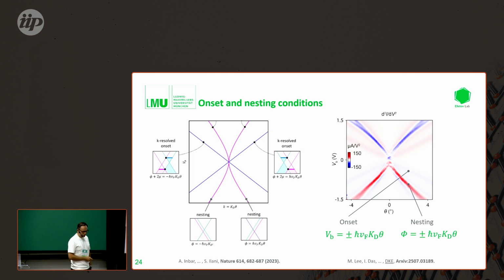Those correspond to different scenarios where energy and momentum resolved tunneling transitions are allowed. Again, to tunnel from one layer to another, you need to match energy and momentum. This X-shaped feature is the onset condition where the Fermi energy in the top and bottom layers coincide, and for a specific twist angle you also find the momentum matching between the transitions, and then tunneling is possible. This is really the linear transition that we can see here, and it's mostly related just to the voltage bias that we can apply.